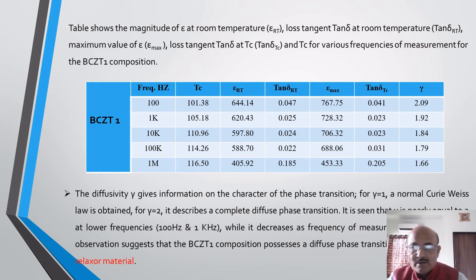Another parameter calculated in my work is the diffusivity gamma. According to the theory, when gamma equals 1, a normal Curie-Weiss law is obtained, and when gamma equals 2, it describes complete diffuse phase transition characteristics. In my observation for BCZT1 composition, the value of gamma ranges between 1.66 and 2.09. That indicates that the BCZT composition possesses diffuse phase transition characteristics and is a relaxor material.